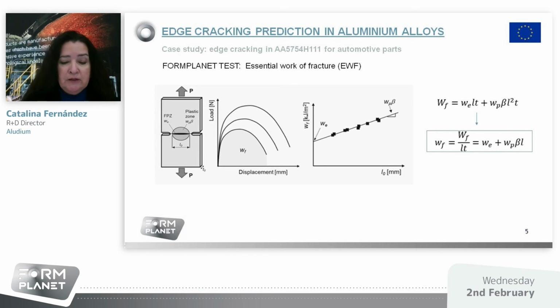Now I will present the result of the essential work of fracture that allows to evaluate the fracture toughness. Here you can see the dent specimen and the experimental determination of the essential work of fracture. Samples with different ligament lengths are tested at a constant displacement rate, obtaining curves as shown in the middle that represent the work of fracture for the different ligament lengths. Then integrating the area under the load and dividing by the initial ligament area, the specific total work of fracture is obtained. Finally, plotting these values against the ligament length, the intercept marks the specific essential work of fracture, while the slope is the plastic work, as you can see on the right.